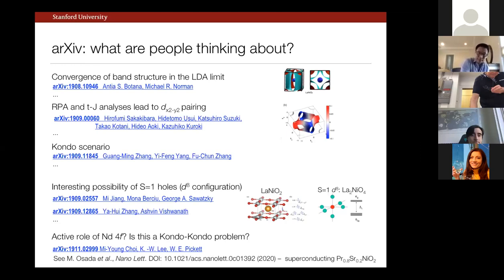So we don't really know the exact answer to this yet, but at least one partial comment we can give is that we've recently published the observation of superconductivity in praseodymium strontium nickel O2. Superconducting properties are rather similar actually to the neodymium case. And I won't go into them in detail, but the main point is that going from neodymium to praseodymium, one expects in general that the 4f level alignments are going to be moving around non-trivially. And so it'd be extremely unexpected to have direct hybridization or coincidental lineup in both of these cases. So in that regard, we tentatively would suggest that this is not crucial to the occurrence of superconductivity, but certainly the question of the 4f moment and how it may or may not couple to the system is an open question.